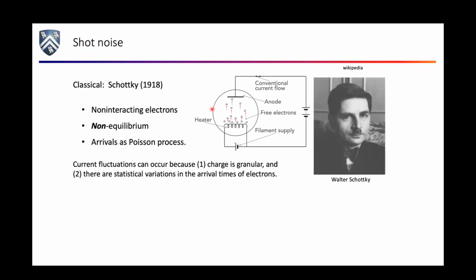What you find is that there are current fluctuations because, statistically, sometimes electrons arrive more frequently in time than other times. Right? Sometimes they happen to be close together, sometimes they're far apart. On average, there's some average arrival rate. But if you compute the mean square fluctuations in the current per unit bandwidth, so we kind of Fourier transform our stuff here, S sub I has units of amps squared per hertz, right? This is mean squared fluctuations per unit bandwidth in frequency space. You get twice the electronic charge times the average current if you just have Poisson distributed particles.